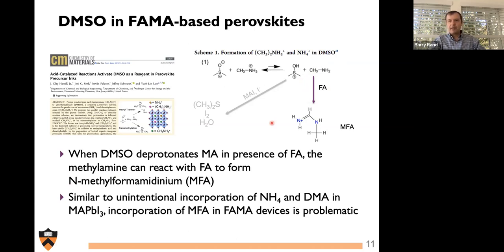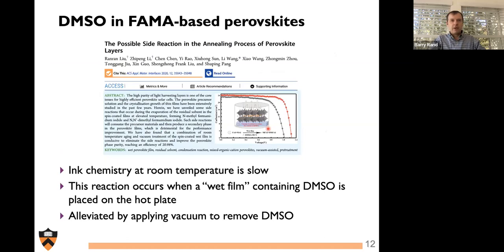It turns out that similar to unintentional incorporation of ammonium and dimethylammonium in methylammonium lead iodide, incorporation of MFA in these mixed FA-MA devices is particularly problematic. One paper that showed this, and you can see here with the introduction of MFA, we see this device suffers considerably poorer performance compared to the device that lacks that MFA.